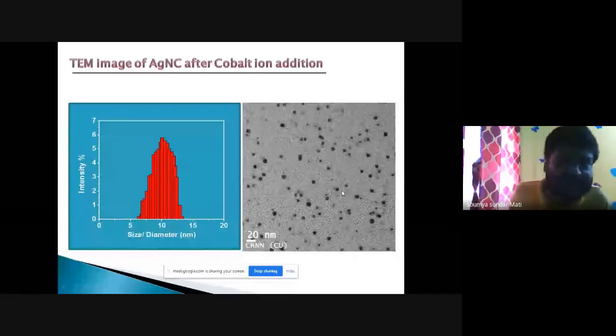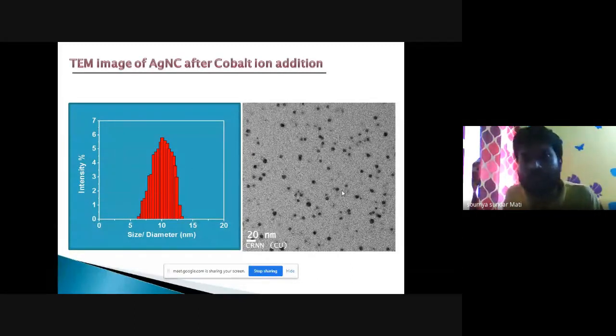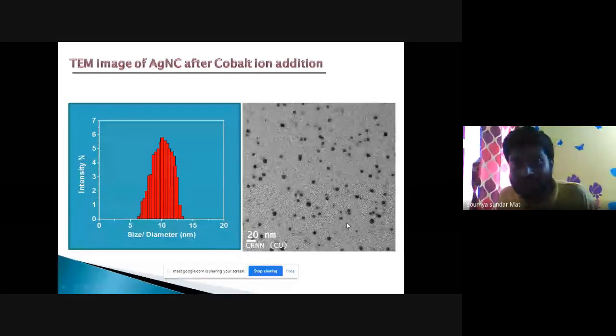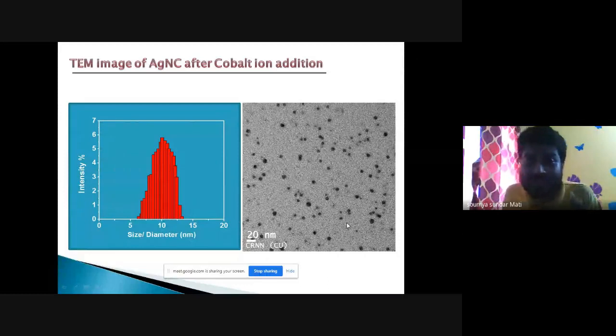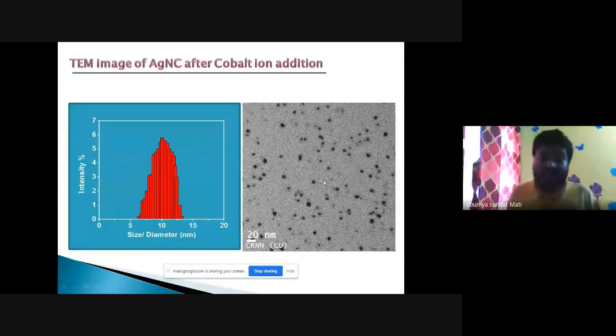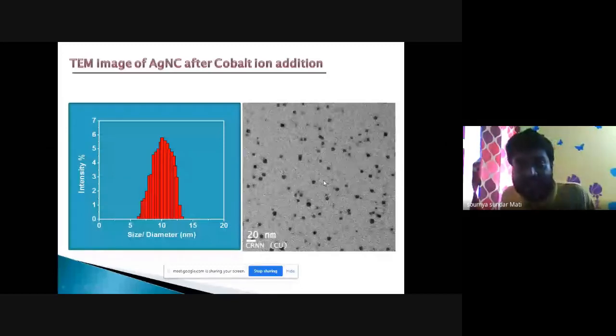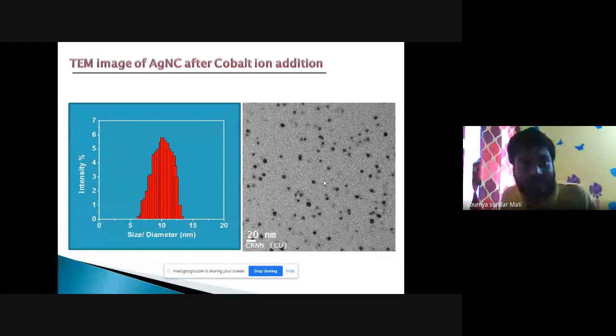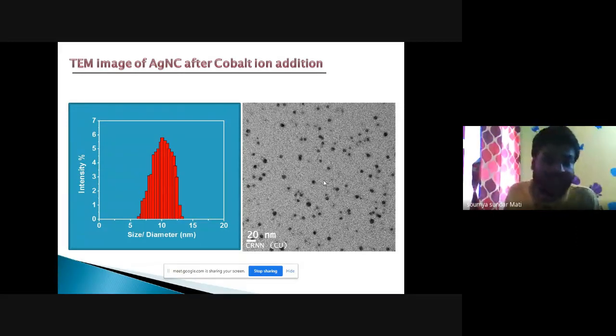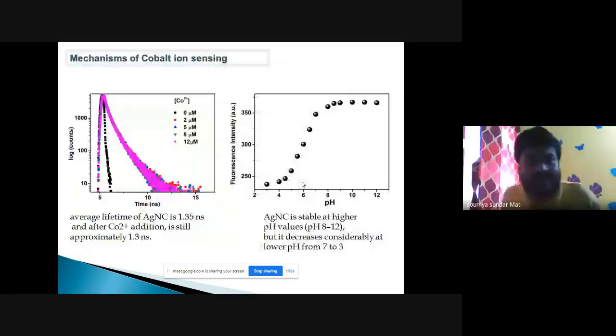Now, the most interesting phenomenon is that upon addition of the cobalt ion, the size of the silver nanocluster increased to 10 nanometer from around 2 nanometer. It can be observed from DLS as well as TEM study. After cobalt 2 plus addition, the silver nanocluster size increases to 10 nanometer. And this 10 nanometer size is due to the aggregation of the tiny silver nanoclusters, forming a non-fluorescent nanoparticle of 10 nanometer size. Now the mechanism of this study.